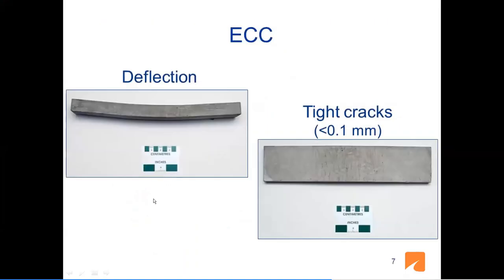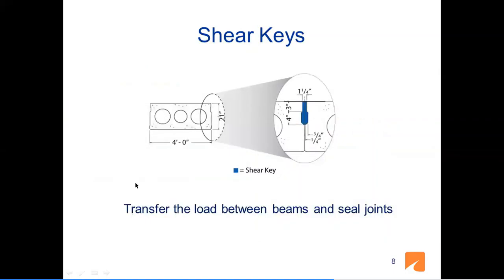And now, same beam I was showing you. On the left-hand side is the deflection from the side. You can see the deflected shape. And now on the right-hand side, you see the bottom of this beam. Many very tight cracks, and these are less than 0.1 millimeter in thickness.